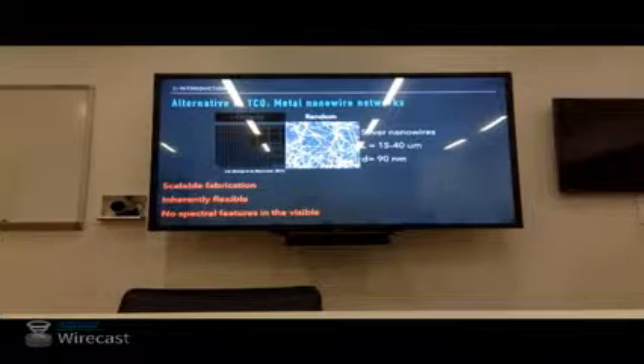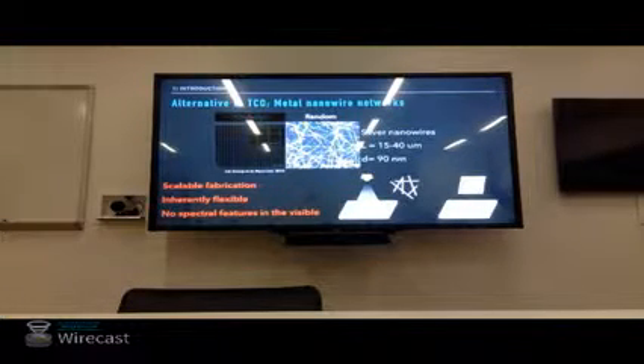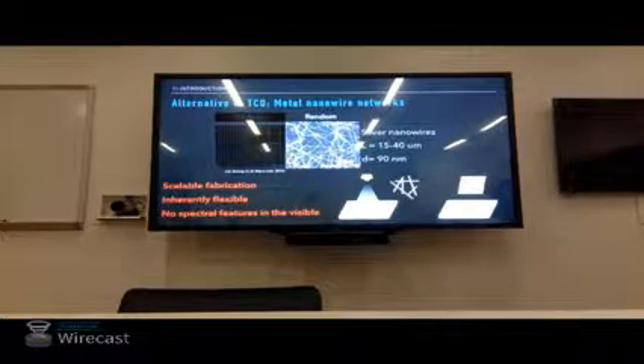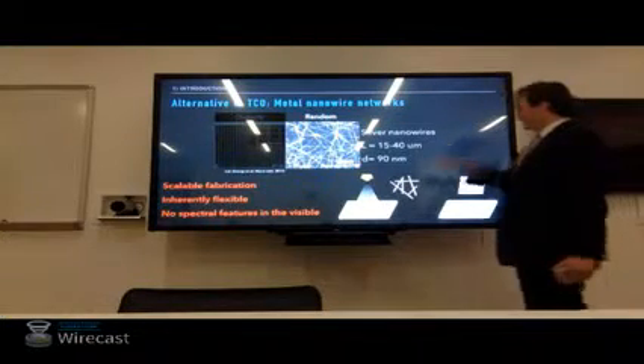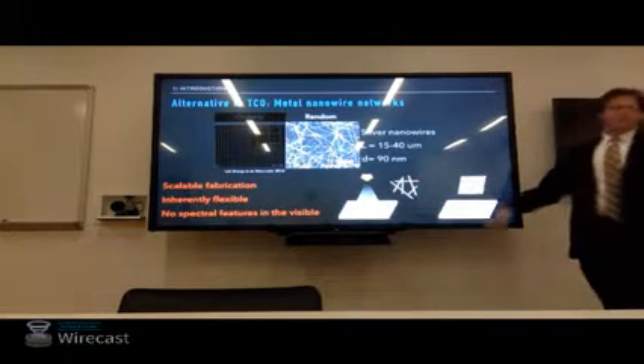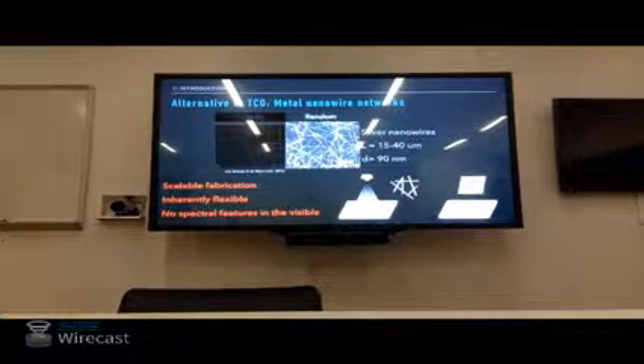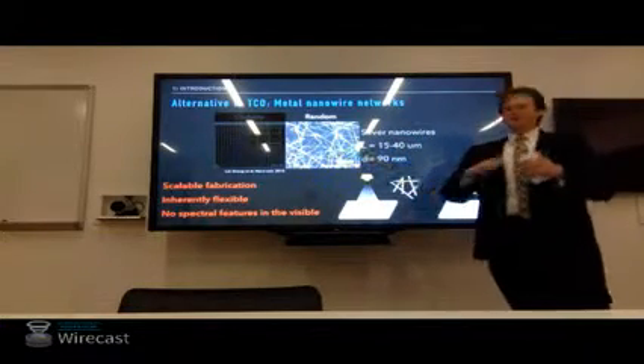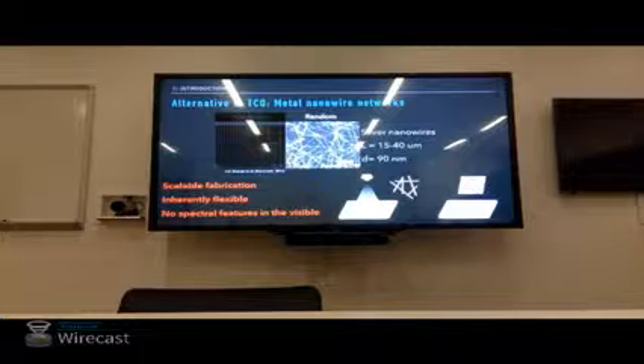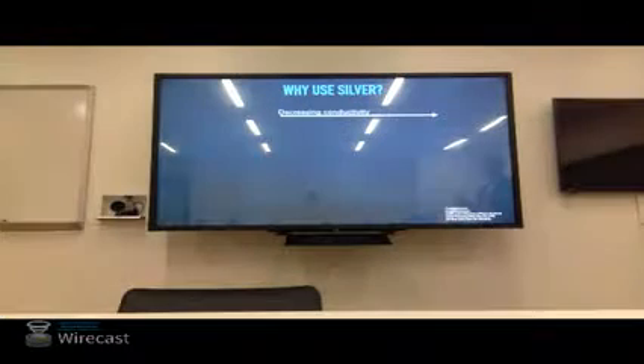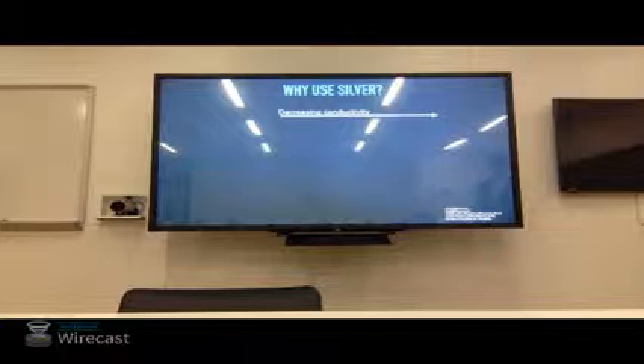So for those reasons, we focus on random nanowire networks, and in contrast to the vapor deposition, we start with nanowires in solution phase, and we can use a whole host of solution phase processing to go from an ink to a layer. Again, we need an interconnected layer because the silver is doing the conduction here, so we need what's called a percolating layer, where we have connections in the nanowires allowing long-range conductivity. At this point, you might be wondering, I said metal nanowire networks, why do they have to be silver?